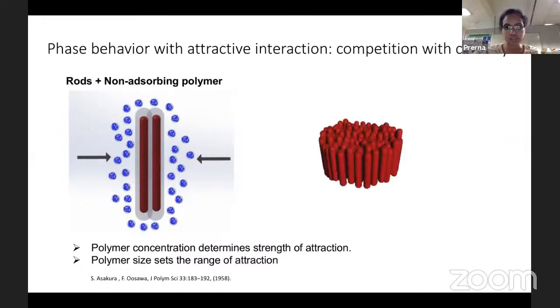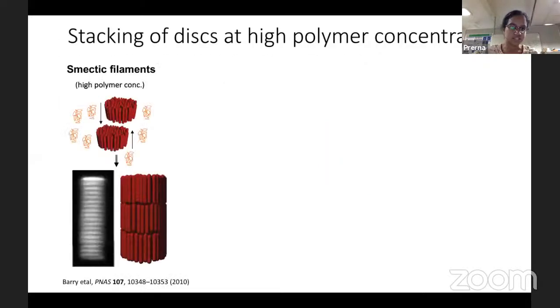So if you have many such rods, you will end up with a disc or a monolayer of aligned rods. The gray zone overlap is maximum when the rods are aligned with respect to each other. So the phase with maximum entropy is the phase where rods are close to each other and aligned along the same axis. If you have two such discs, they can stack up on top of each other through the same interaction. Now you should think of each of these discs as a colloidal particle undergoing this interaction with these non-adsorbing coils, what we call depletion interaction. And so they stack up on top of each other.